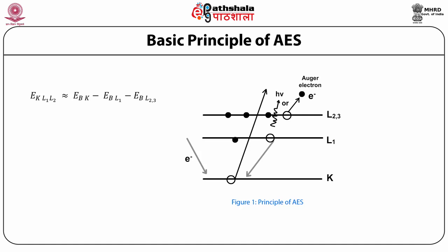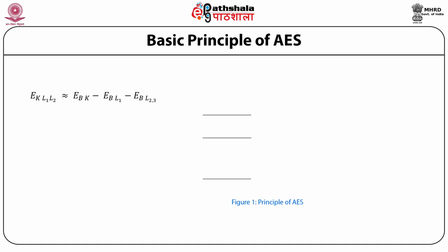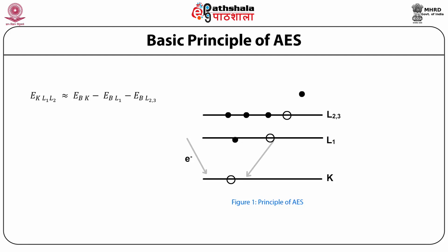During this transition process, the energy difference between the outer and inner shell electrons may cause emission of either a characteristic X-ray photon through a radiative process or an Auger electron from an electron shell through a non-radiative process. Auger is a radiationless process where an excited ion decays into a doubly charged ion by ejecting an electron. The kinetic energy of an Auger electron is approximately equal to the energy difference between the binding energies in the electron shells involved in the Auger process.